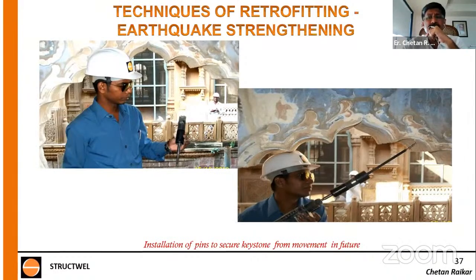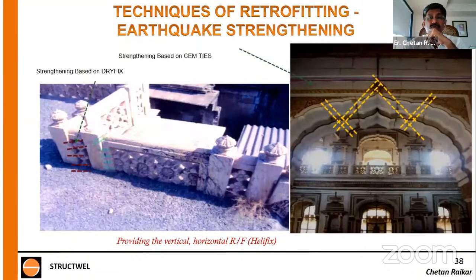Helifix pins are about 450 mm span typically. So you grout them, so you drill them through the crown stone into the neighboring stone. What you see in the right side photograph is how the crown stone is fixed with helifix steel pins. Because helifix steel pins are more expensive, we have also started using knurled SS pins. Drill a hole, put the pin, and grout the annular space with epoxy. This also is effective. It is quite economical, but helifix pins are very fast to install and quite effective, though a bit costly.